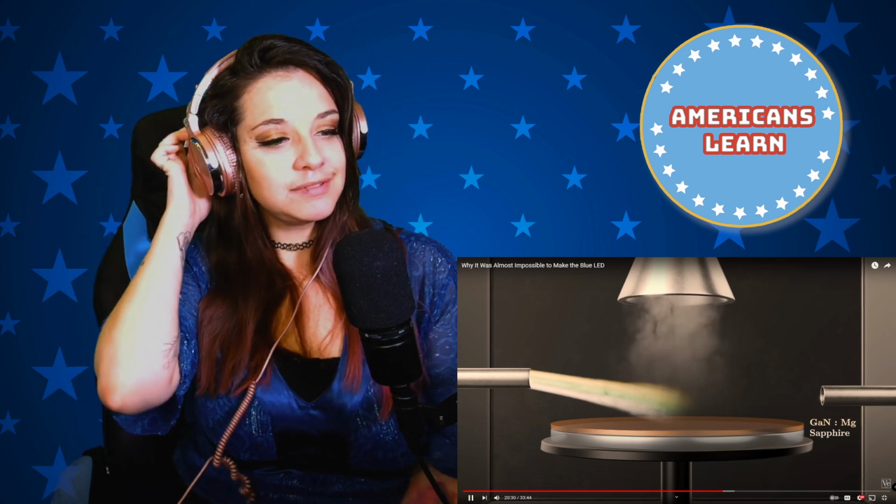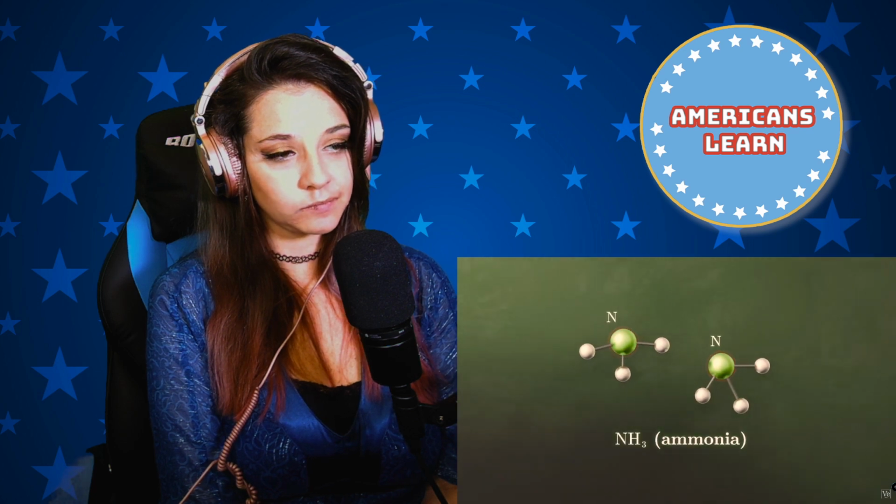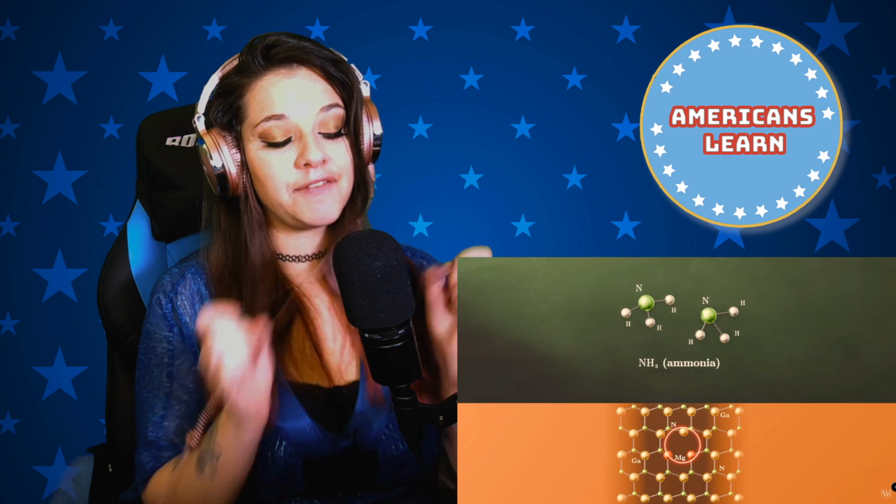You know? His work also revealed why the P-type had been so difficult. To make gallium nitride with MOCVD, you supply the nitrogen from ammonia. But ammonia also contains hydrogen. Where there should have been holes in the magnesium-doped gallium nitride, these hydrogen atoms were sneaking in and bonding with the magnesium, plugging all the holes. Adding energy to the system released the hydrogen from the material, freeing up the holes again. And giving it space.